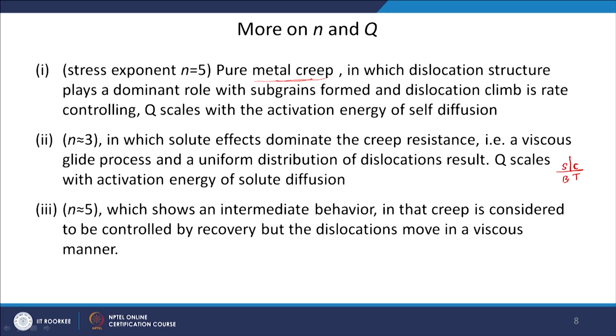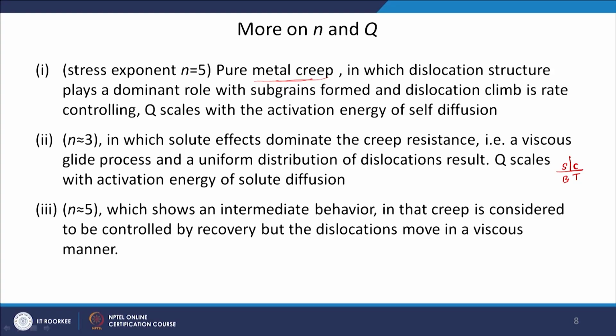What it does when this solute go and sit in the dislocation core, now if suppose you are applying stress, the dislocation wants to move, it has to carry all this solute atom also with the dislocation. Sometime if you are applying higher stresses, dislocation velocity is sufficiently high, then sometime it can also leave this solute atom and will be free to go. But sometime if the stresses are low, it has to carry all this solute atom also with it. So, the stresses to move a dislocation will be now different, because it has to carry this extra load. So, in those cases you have n equal to around 3, when the solute effect dominate the creep resistance. A viscous glide process and a uniform distribution of dislocation result.